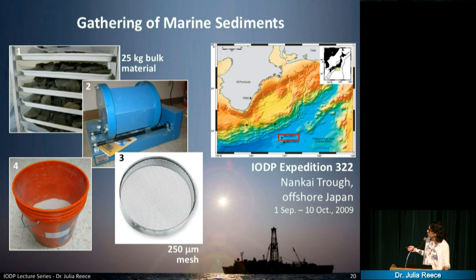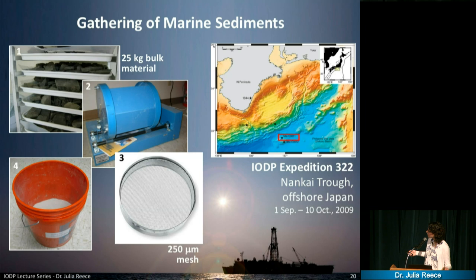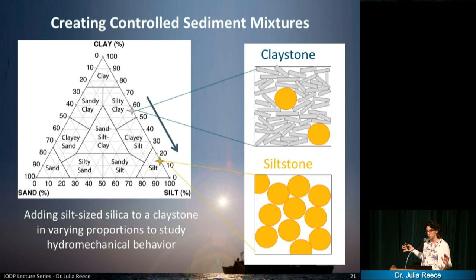And what we did is we collected just a bunch of chunks that were left over from other projects. And then I used this ball grinder to get it all down to a small fine powder. We sifted and we mixed it, and then we ended up with this Home Depot bucket full of powder that is all one batch, homogeneous, and so really good for repeatability. And then so this is now this mudstone from offshore Japan that is represented by some silt grains and some clay particles. So we are located right here.